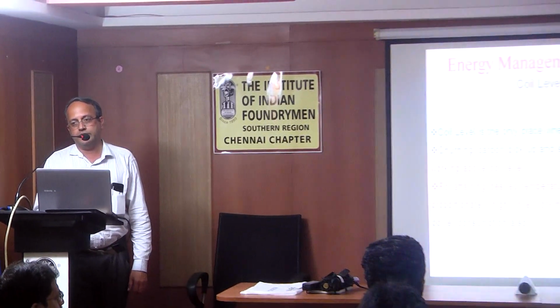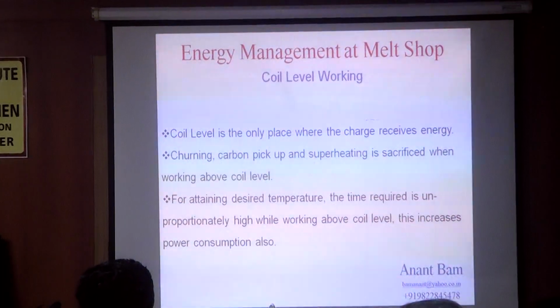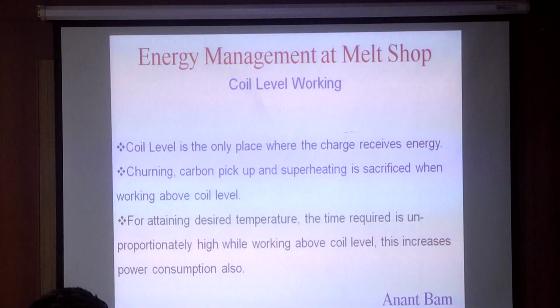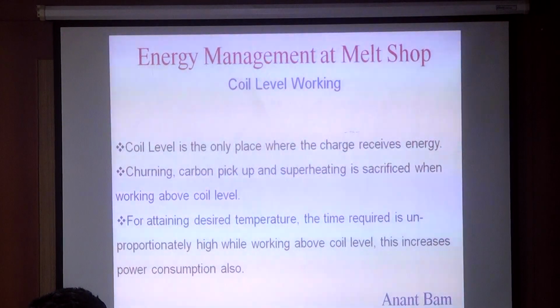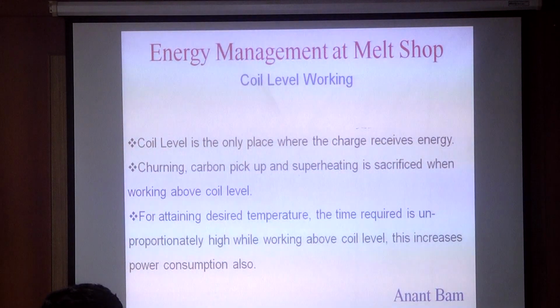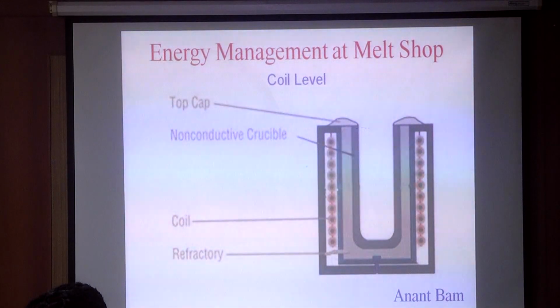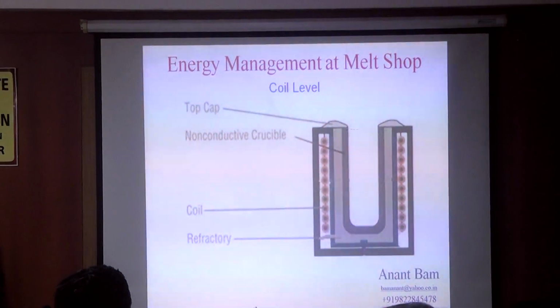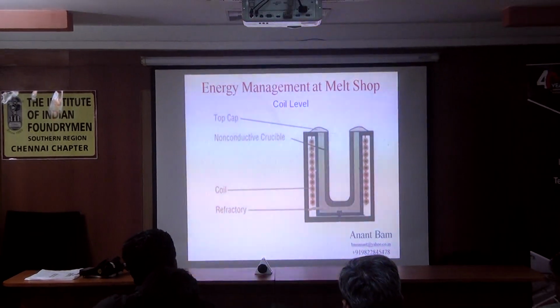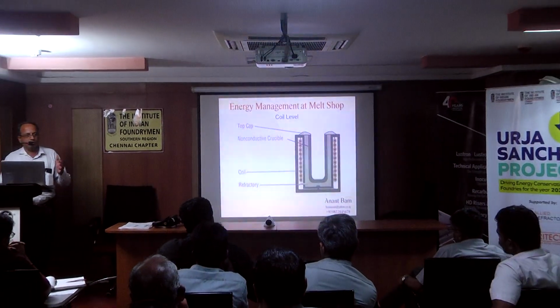Coil level working. That's the only area which receives energy. Not below it, not above it. So if your coil is placed much above, the bottom remains cold. If you are charging too much metal by raising your crucible height above the coil, that remains cold, and the energy is received in the middle. So whatever is within the coil, it receives energy efficiently. And if you try to increase your holding capacity or dispensing capacity by raising the lining height, then you are not only delaying the heat, you are also consuming more energy.